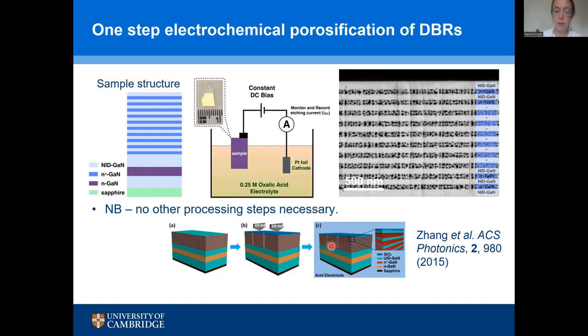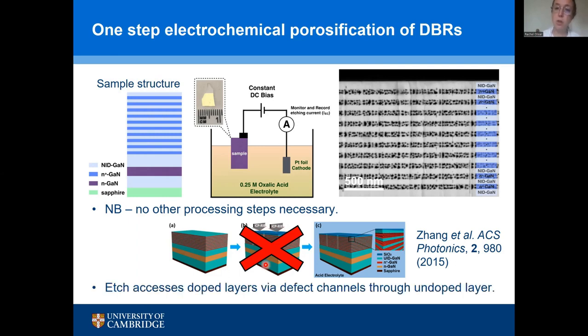That's perfectly effective, but it is quite a complex multi-step process, and it limits what you can do next with the etched structure you've made, because your device architectures are then going to have to work around this trench formation. But our process doesn't do any of this bit in the middle. We don't cover the surface with silicon dioxide. We don't make trenches. Our etching is happening from the top down. In this case, the etchant's going through these undoped layers, several of them you can see in my picture.